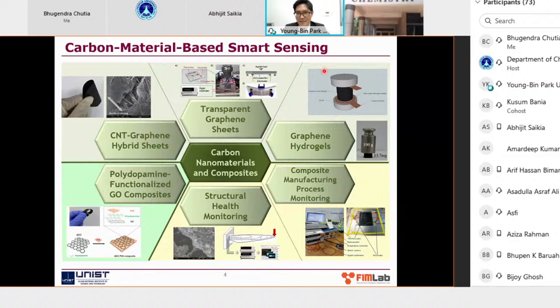Our target was a sensor. It's a physical sensor that could measure the pressure, compression. So in that, maybe I can go back here. Okay, so this one, right? Yeah. So here, basically, it's a very, very simple and basic concept called piezo resistivity. So if you measure the change in electrical resistance as you apply compression as shown here, then because the hydrogels are so compressible, they have a very high sensitivity under compression. So we particularly looked at the mechanical compression measurement. I have one paper published on this topic, and if you email me, then I'll be more than happy to send it to you.